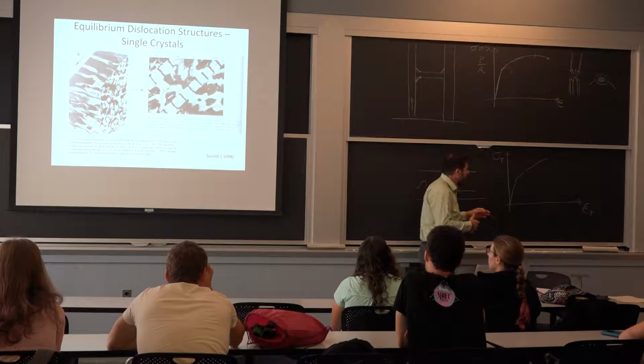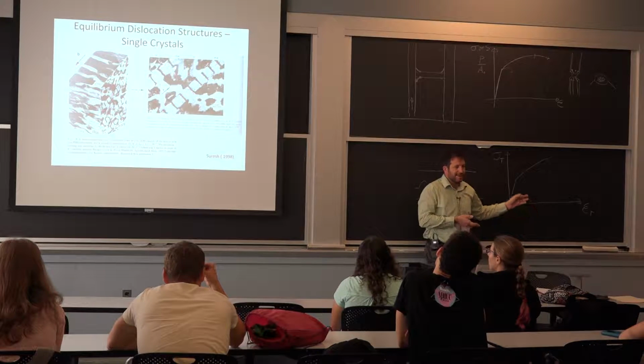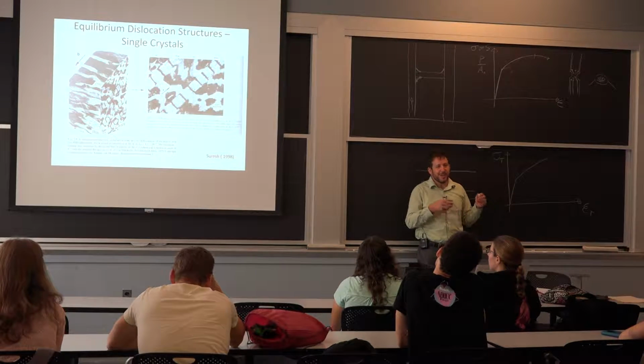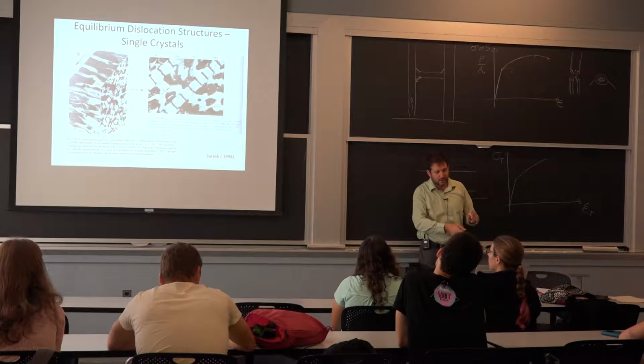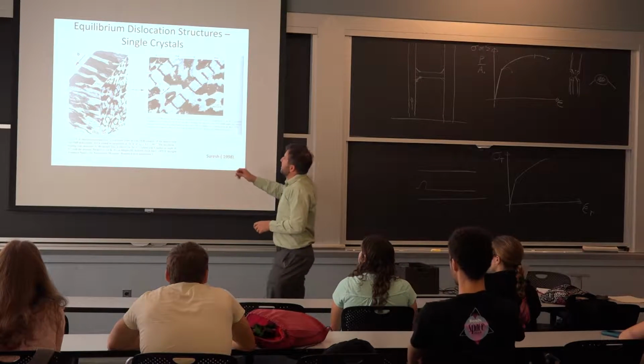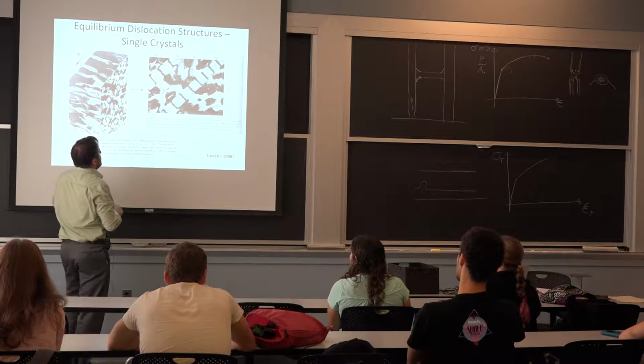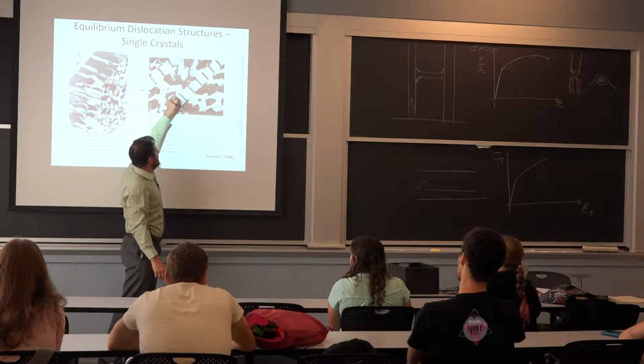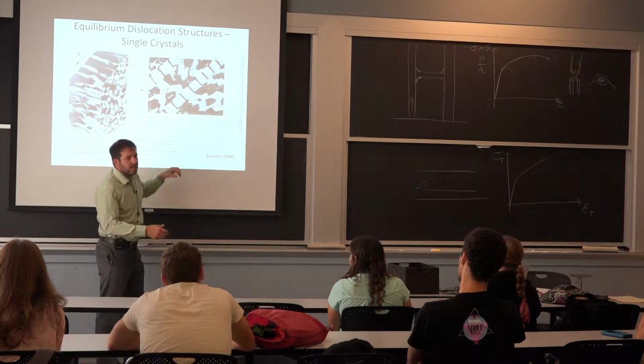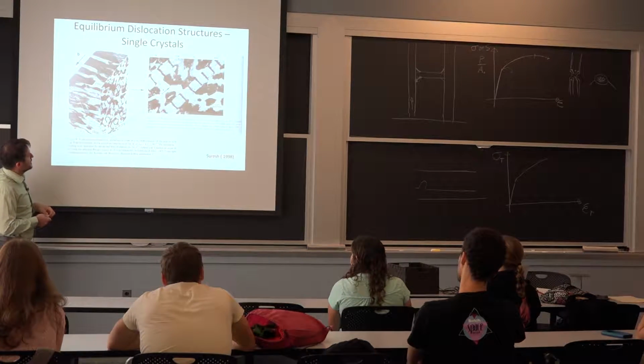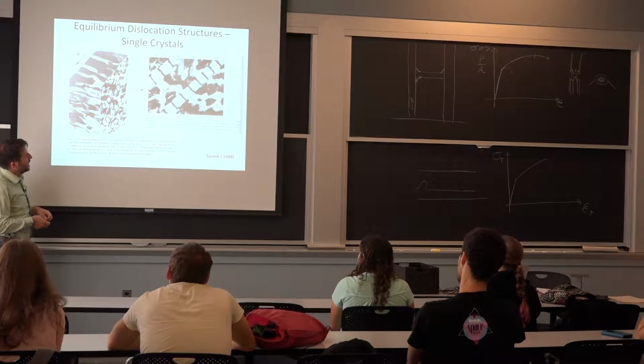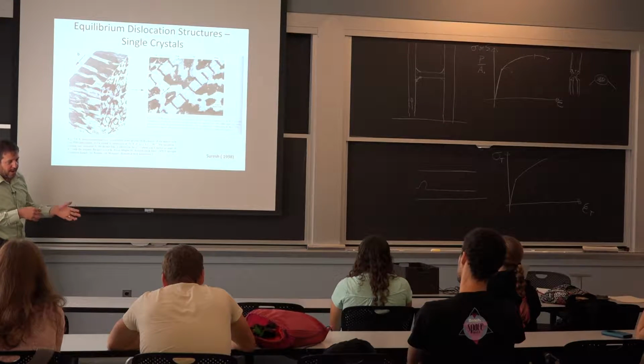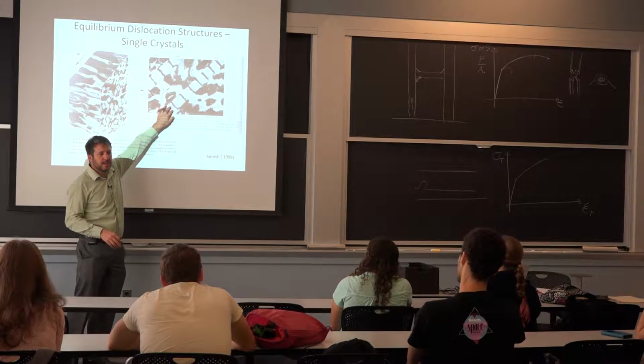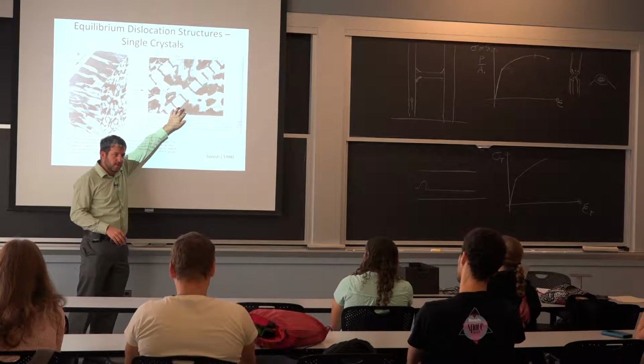In just a rolling operation, it doesn't necessarily lead to a very nice looking structure under the microscope. But when you do the cyclic deformation, this is what I'm showing here, you can get these different zones where you have very little dislocation, and all the dislocations are lined up in walls. And it is essentially a natural way for the material to segregate an area of activity for deforming and an area of recovery for deforming.